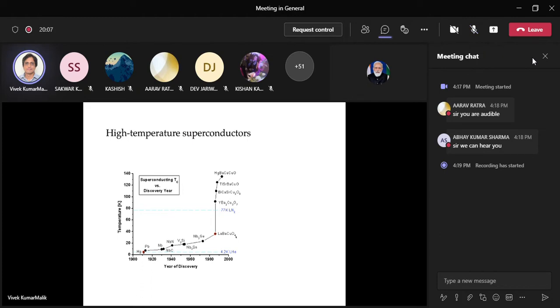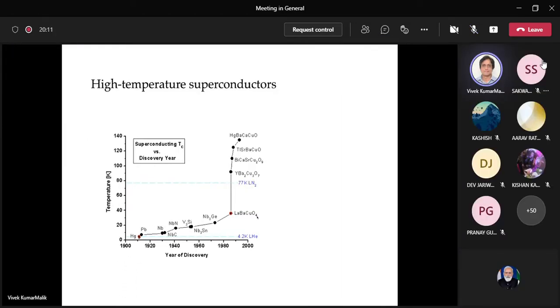And very soon, within a year, similar compounds were discovered having a TC of more than 77 Kelvin, like yttrium barium copper oxide, YBa2Cu3O7, which is called the 123 material, having a TC of 91 Kelvin. Then bismuth calcium strontium copper oxide, and so on. So this family is usually called the cuprate family, because the essential feature is the two-dimensional copper oxide planes within the system, which is an essential feature of all these oxide superconductors. So they are called cuprates, and the maximum is around 135, 136 Kelvin, in the HgBaCaCuO superconductor. So within 1 or 2 years, the TC was increasing.